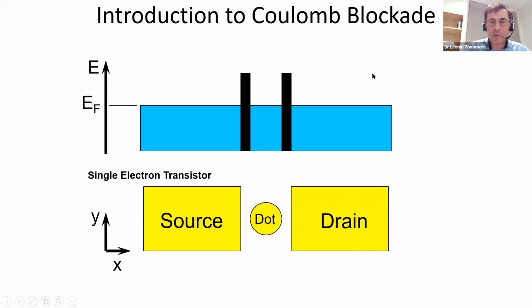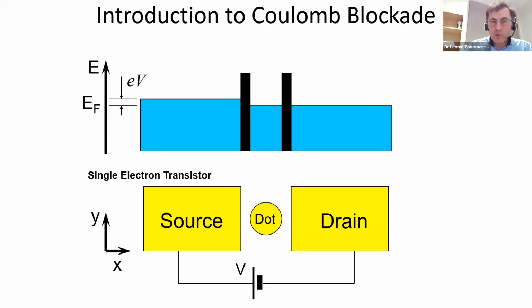So this is in real space, and on the top, this is the energy potential. If we apply a voltage between source and drain, we change the energies in these electrodes, and because we raise the potential of one of the contacts, due to the potential difference, electrons start to tunnel through the tunneling barriers and current flows. However, if the dot is really, really small, then in order to transfer one electron to the dot, we have to charge it. But a small dot means small capacitance. And in order to charge such a dot, we have to provide some energy for this electron. This energy is e squared divided by the capacitance of this island, where e is the charge of the electron. So if capacitance is small, this energy is large. And if this energy is larger than eV that we are applying, then current cannot flow. This is called Coulomb blockade.